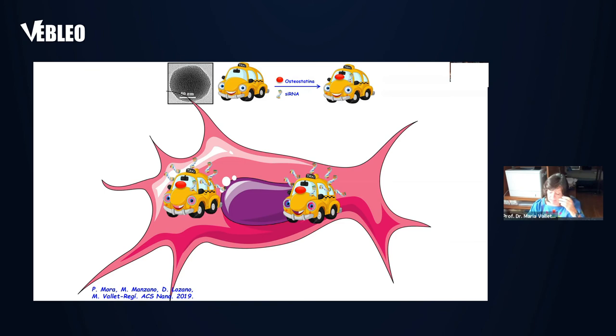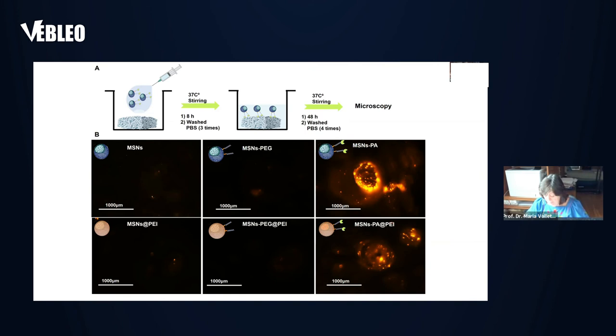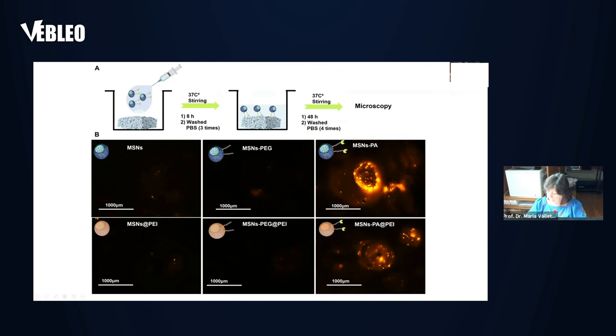Nanoparticles are loaded with osteostatin and then coated with a polymer decorated with siRNAs and the whole ensemble travels to and is internalized in the cells. The carrier is internalized up to 85% for the full system. This image confirms the cell internalization of our nanoparticles with the silencer inside. Therefore, we have a siRNA carrier that solves its two main drawbacks, enabling an effective treatment. Let's watch a video illustrating this process.